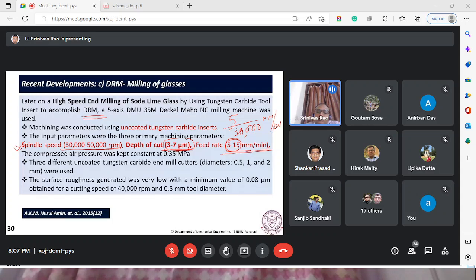However, if we can go for this, you can see the surface roughness generated is very low, with a minimum of 0.08 micrometer. This is the Ra value, and Ra 0.08 is very good. It is basically 80 nanometer. Normally, in normal precision machining such as turning, it is around 0.5 micrometer. 0.5 to 1 micrometer is considered a very good roughness for macro machining. Less than that is obtained here, which means the glass surface generated is quite smooth. But with these parameters of depth of cut and feed, the material removal rate will be very low.